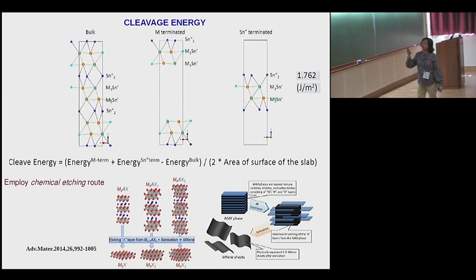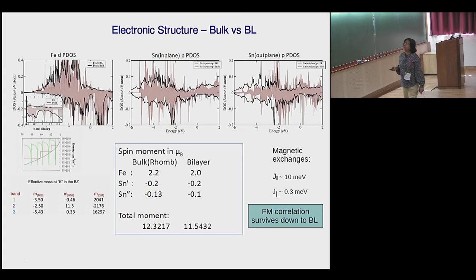And what we found is that, of course, you can calculate the cleavage energy, what will be necessary to make such a kind of 2D thing, and from the calculated value, which is like 1 to 2 joule per meter square, we think the creation of such 2D materials is possible experimentally. And by going to the 2D, a lot of changes happen in its electronic structure. Primarily, there is a huge dimensional influence, so there is a dimensionality reduction. So you have Van Hove-like features if you look at this bilayer density of states. The magnetism remains though pretty much like the bulk.